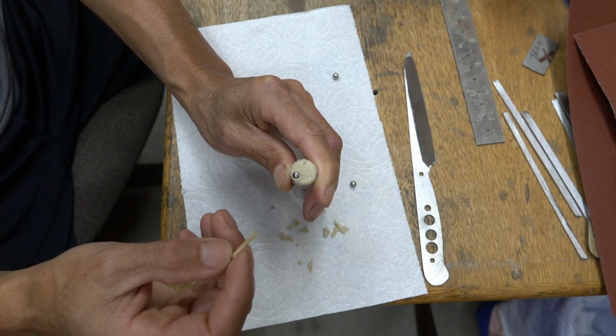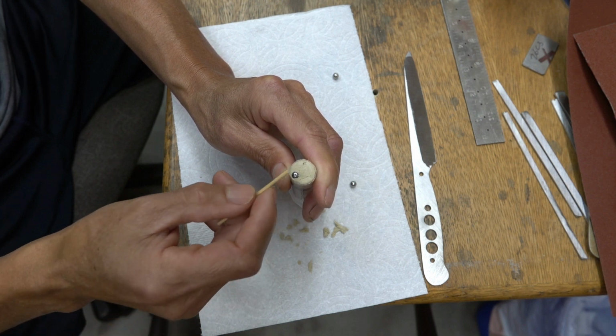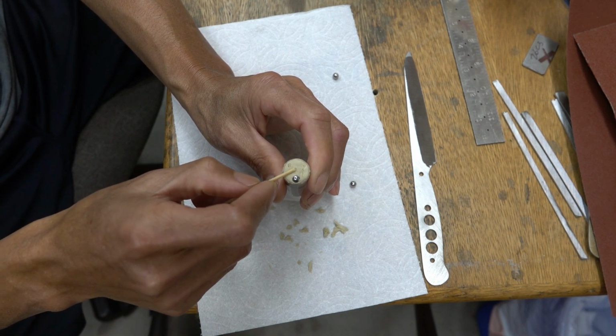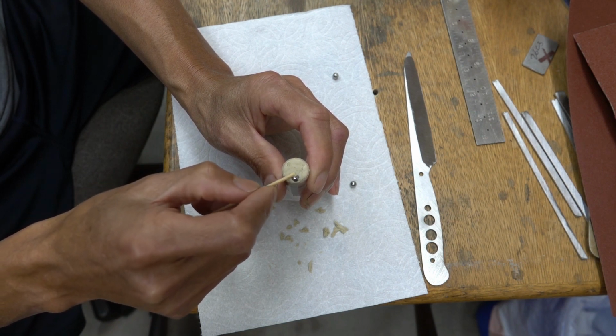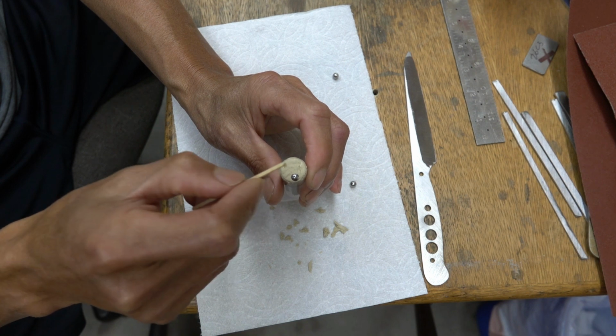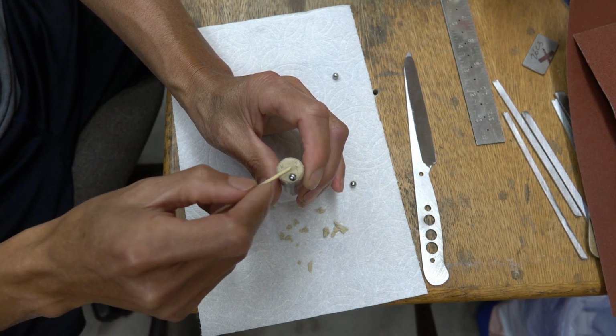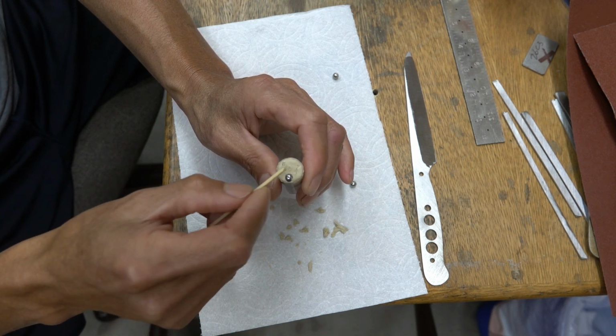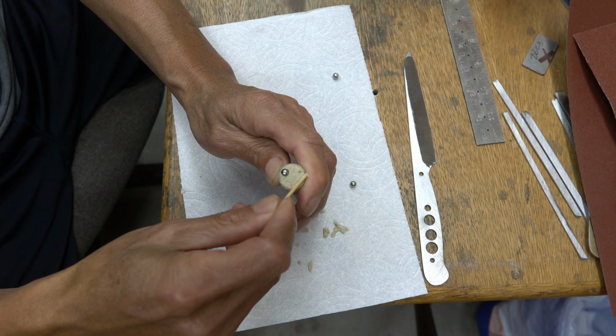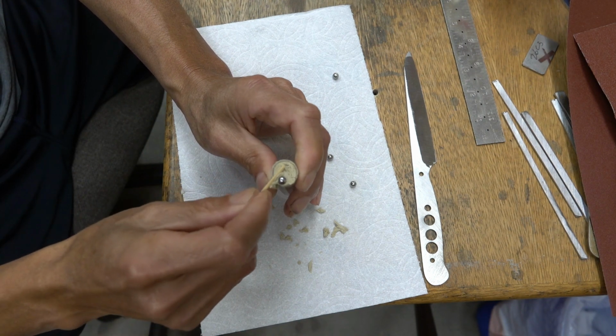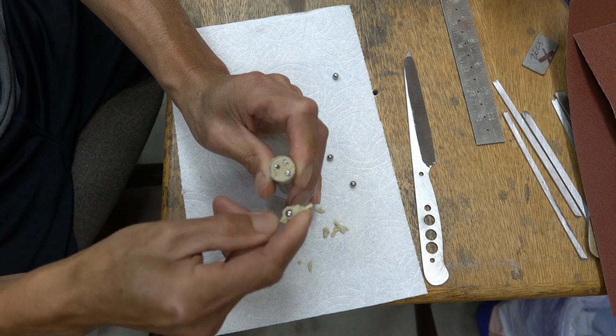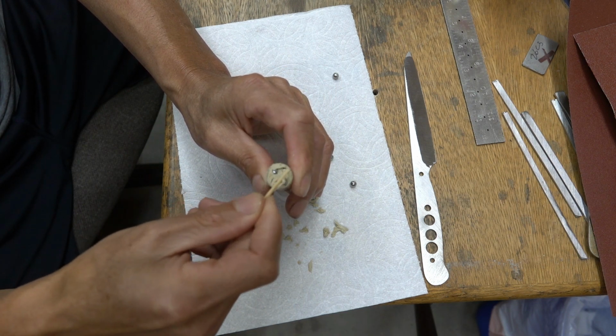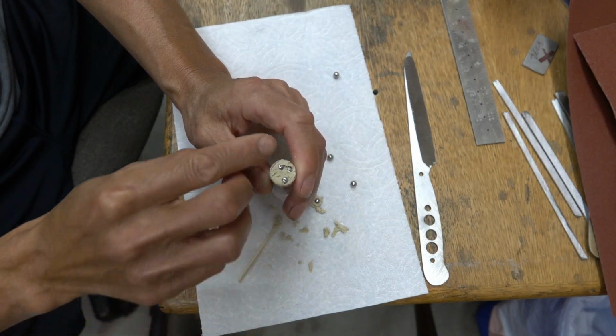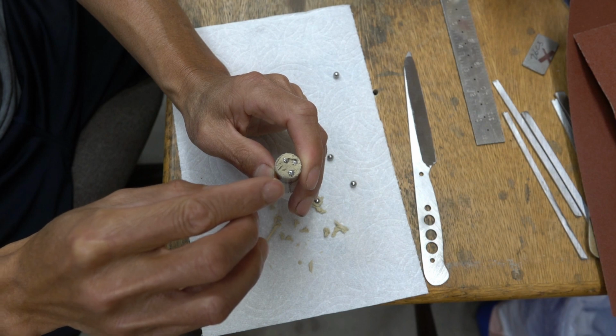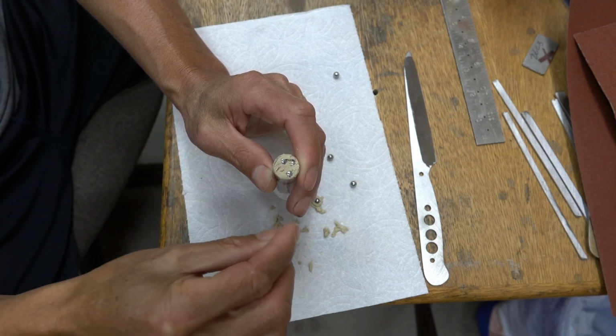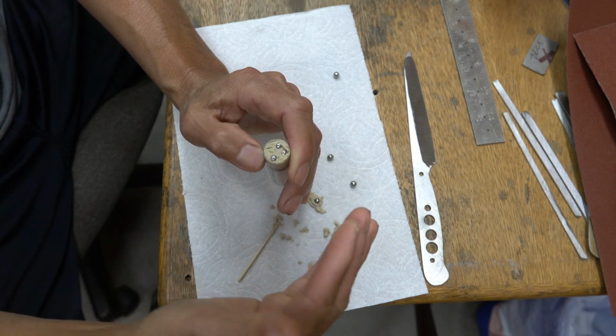I try to look at the way that I can qualify what is wear resistant, whether the heat treatment did produce a stronger matrix that can hold on to the carbide. When the matrix is stronger, then the protrusion of the carbide will be higher. That means overall the population that got dislodged, you're going to see, yeah, it looks like I don't have any more carbide below there. Oh, there's some, right? Well, I did when I made these things. So overall, if the matrix is stronger, then we see the surface will be decorated with a lot more carbide because it didn't get dislodged. So you can compare side to side.